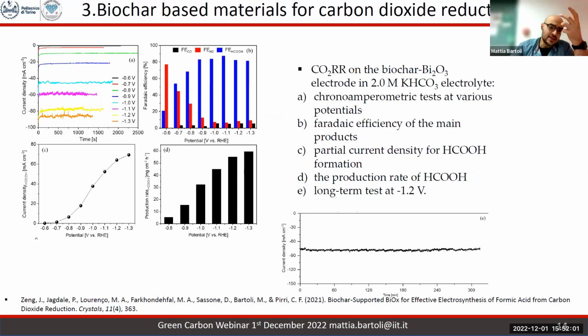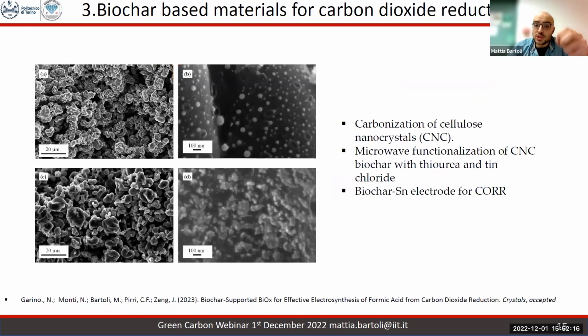So, with this study, we proved that we can use advanced engineered biochar tailored with a non-noble metal to convert CO2. So it's an effective catalyst. We tried also something more fuzzy. We use cellulose nanocrystals produced by fermentation, and we tailor them with thiourea and tin by using a microwave approach, to create these carbon spheres with nanoparticles of tin.